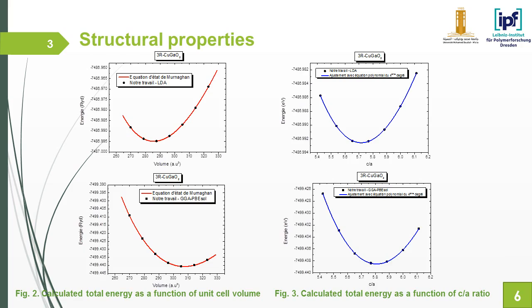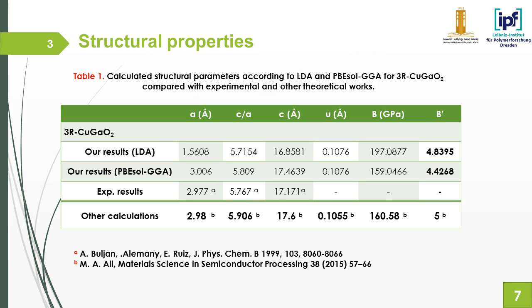The relaxed equilibrium structure parameters, the calculated lattice constant, the internal parameter, bulk modulus, and its first derivative were obtained by fitting the total energy versus the volume and the ratio c/a to Murnaghan's equation of state and with a fourth degree polynomial equation, as shown in figures 2 and 3 respectively. Here, this table lists the calculated structural parameters according to LDA and PBEsol-GGA for copper gallium oxide, which are in good agreement with theoretical and experimental results.